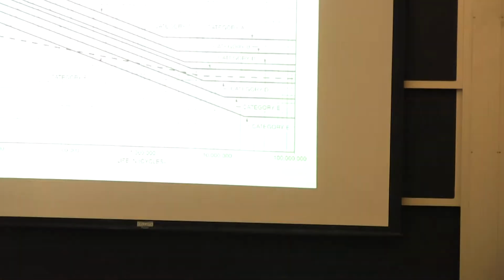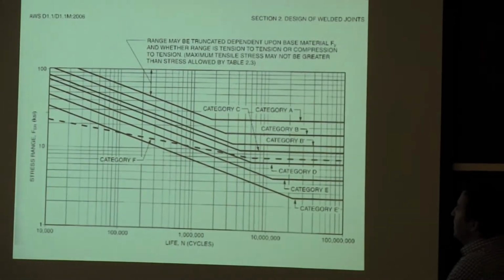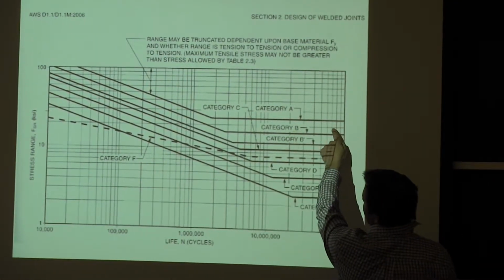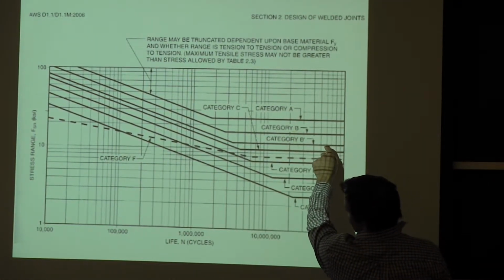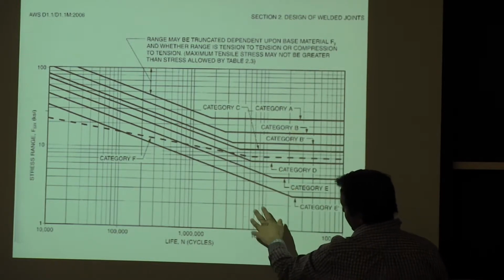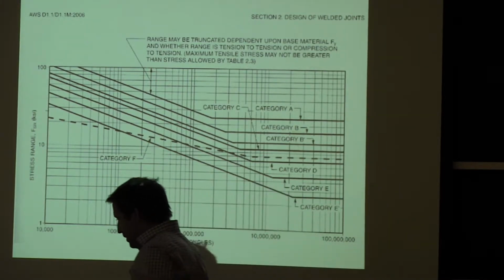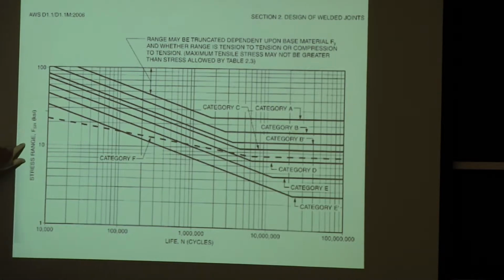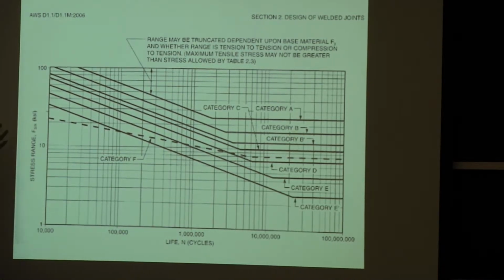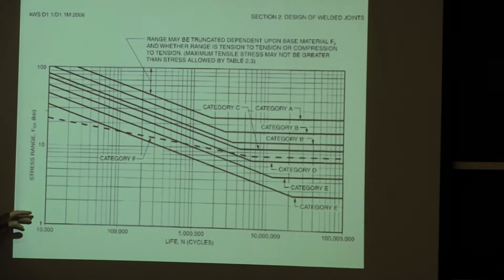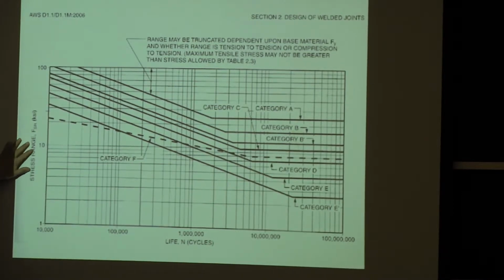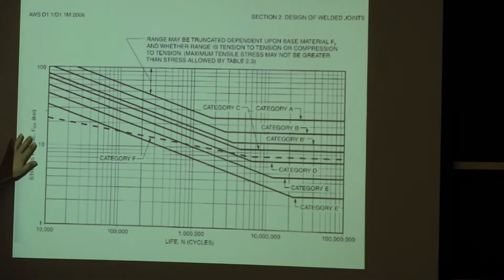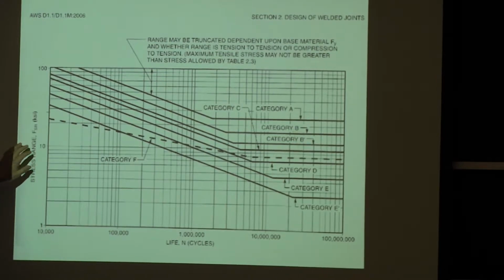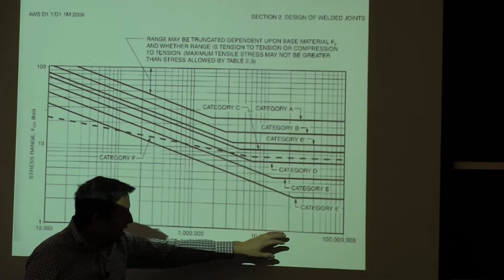Plates and shapes. What you can see between the base material here, you have an allowable stress range. So we're talking about fatigue here. This is slightly different, where the stress range is essentially your maximum stress minus your minimum stress. It's not the amplitude. The amplitude will be half of this axis. And the life here is what you allow to tolerate.